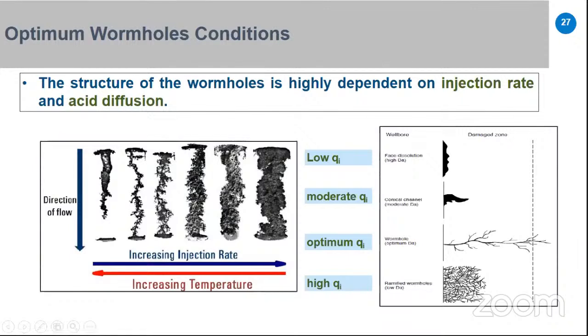This connects the small pores of your reservoir, and it is not good because it will need much more volume of acid. So this is the core showing what is happening from low injection rate to high injection rate. As we see, from low injection rate we have only face dissolution. If we increase it, the wormhole extends until we reach the optimum one, a branched wormhole. Then if we increase it further, you connect the small pores to your wormhole until you end up with an ramified wormhole.